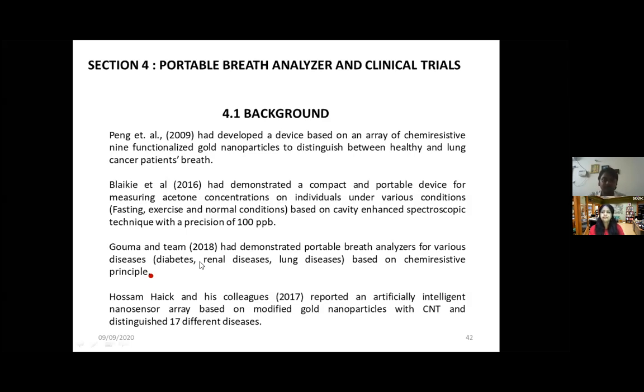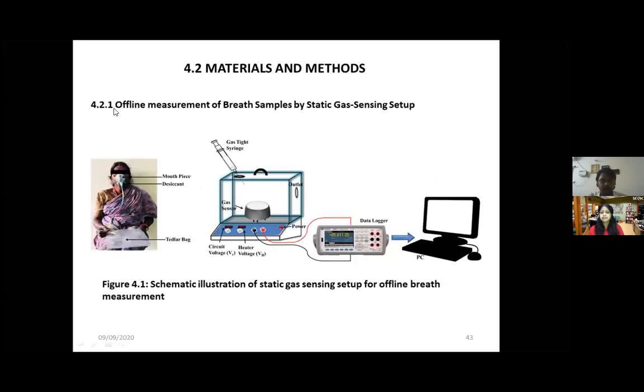Breath analysis can be performed either through online or offline analysis. For offline analysis, there's a desiccant here to eliminate the humidity. This is silica gel, which comes in the packing of electronic components. We place the silica gel here. The patient blows and we collect it in the Tedlar bag. Similar to the static gas sensing setup, we take it in the gas-tight syringe and give it as an input to study the response of the breath print.